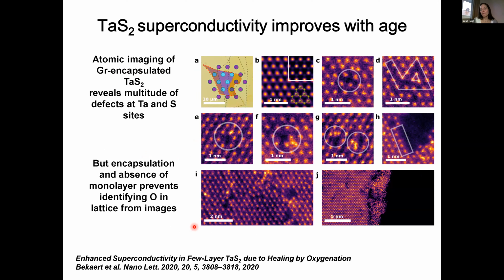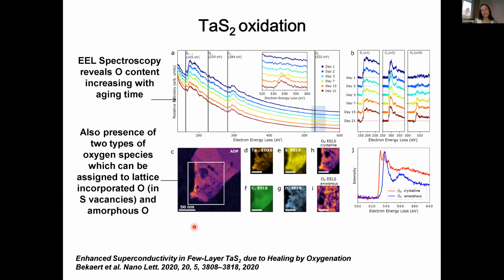And for that reason, we had to move away from the imaging. We tried annular bright field, we had lots of different types of STEM imaging. We weren't able to see the single oxygen vacancies in the lattice conclusively. So instead, we did a study using electron energy loss spectroscopy. We looked at the material as a function of time, so day 1, day 2, day 3, up to 3 weeks old. And we were able to see that there was indeed an increase in oxygen.